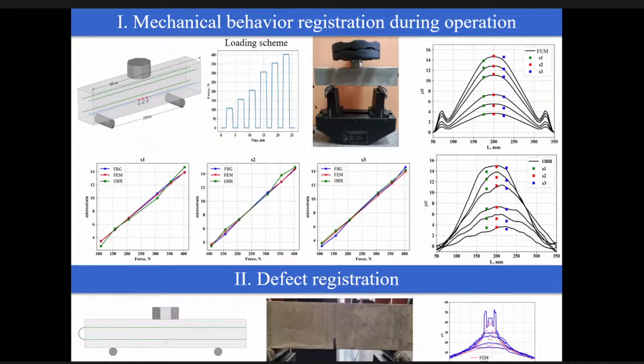And the second part of the work was devoted to the defect registration using fiber optic sensors, and the possibility of using this embedded distributed fiber for recording the appearance and the development of defects has been demonstrated. And to conclude, despite a number of limitations, the considered approach can be used for various laboratory studies, despite the fact that the fiber optic sensor didn't have any additional coating to protect it. So in the laboratory condition, we can use that. Thank you.